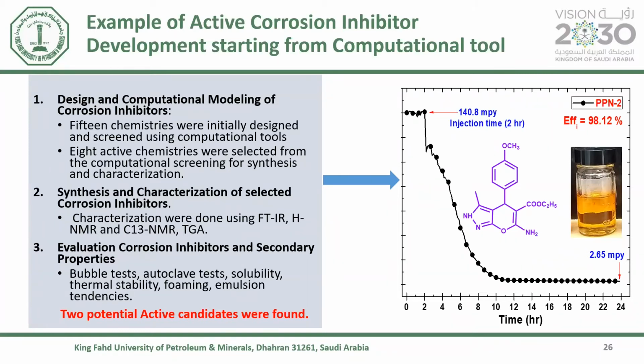Then we went further for characterization. So we did a lot of structural characterization like FTIR, proton NMR, carbon-13 NMR, and TGA to test for the thermal stability of these molecules. Then we did corrosion evaluation and some of the secondary property testing. So at the end of the day, we were able to get 2 potential active candidates. You can see the result here.